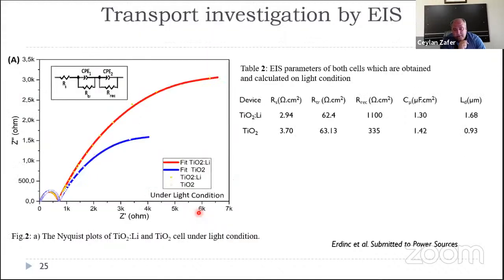And recently we checked with impedance spectroscopy whether it is really so effective for the device performance and the charge carrier transport. And you see the recombination resistance is so high compared to the non-lithium doped material. And this means that the recombination rate is very low compared to the earlier one. And the transport is unchanged.